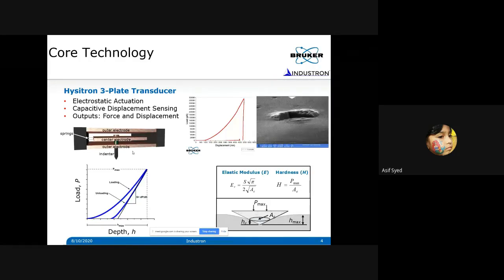That is when you have something like this. I'm showing a transducer over here. You can see there are three plates. The center plate is suspended by a spring, and there are two outer electrodes, and there is a gap between these plates, right? So now if you apply a high voltage at the outer, bottom electrode, it is going to generate electrostatic force, and then it will attract the central electrode downwards. And the indenter probe is mounted on the central electrode, and that's how you create force, and that force is being applied onto the sample, right?